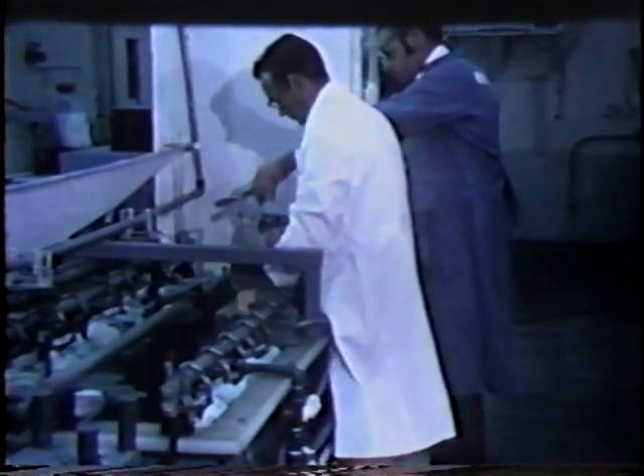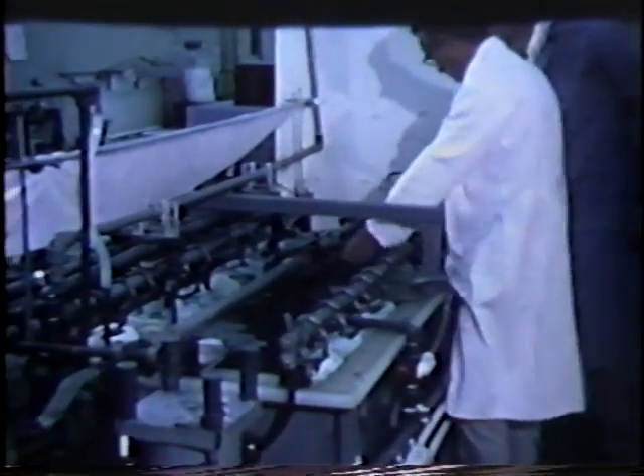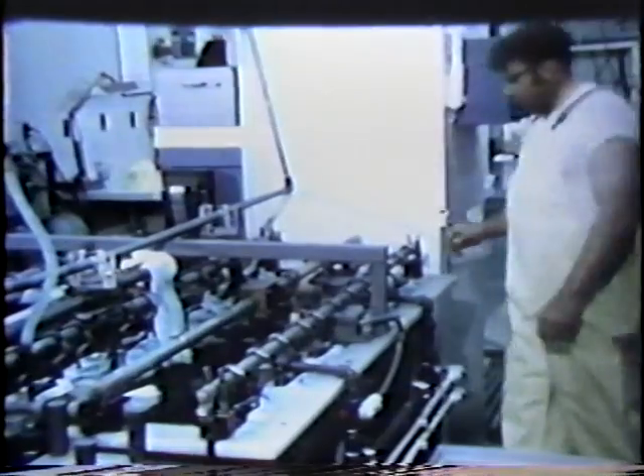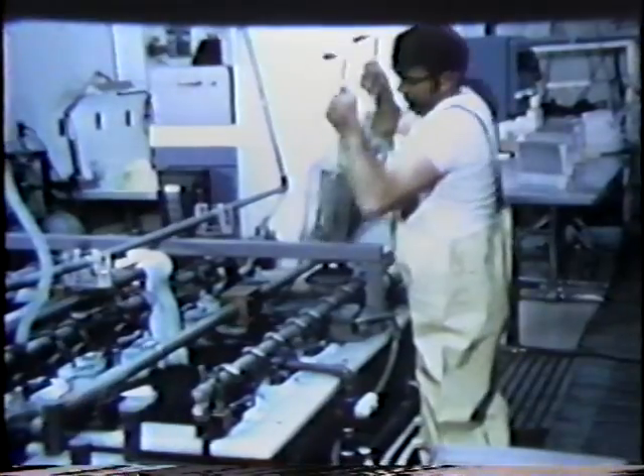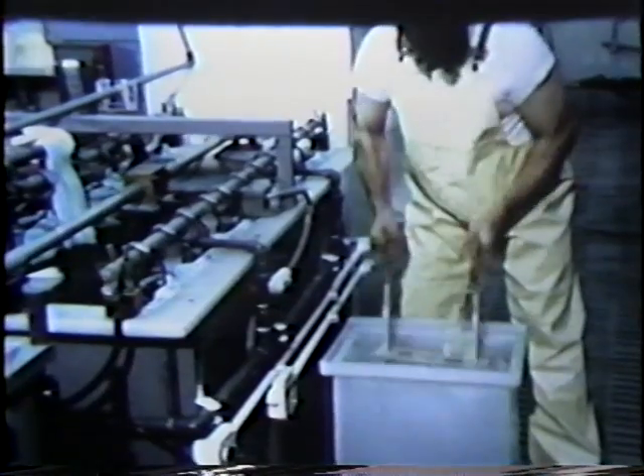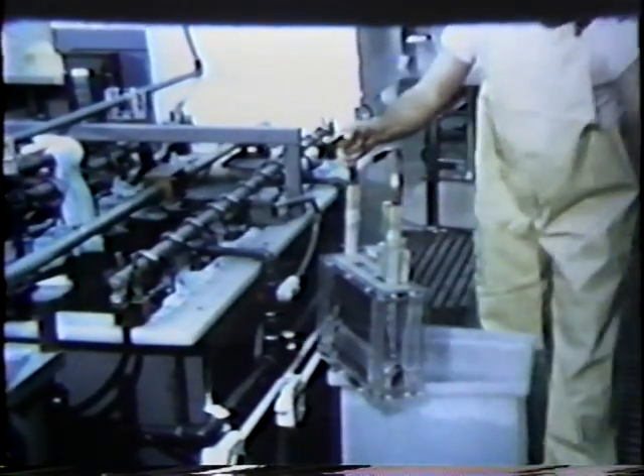This low number of cycles was made possible by development of shielding techniques which minimized abnormal deposits of nickel. Interstage numerical control machining is done between the first and second cycles, ensuring a uniform buildup of nickel structure in the most economical manner. In addition to serving as a closeout for the coolant channels, the nickel acts as the load path for transferring the injector end pressure loads into the cast aluminum backup structure. The extensive use of welding eliminates bolted joints and seals, minimizing leak paths, reducing the cost for joint preparation, and lowering weight.